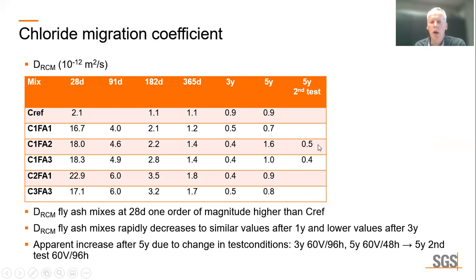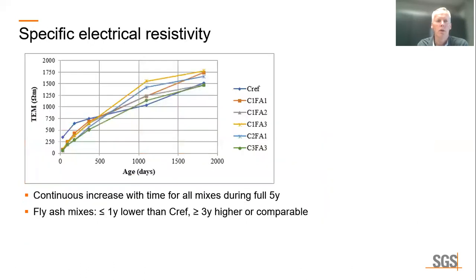And we see that now we obtain a test result which is comparable to the one after 3 years. So this is the result that we believe in after 5 years.